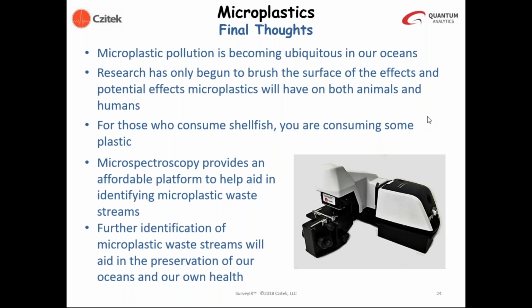So the first question, how long did the analysis of microplastic samples in the presentation take? Well, the collection of the infrared spectrum itself, measuring it, was a maximum of a minute. You have to collect the background spectrum, which is a blank, for those of you who aren't necessarily that familiar with FTIR. So it's a minute for the background and a minute for the sample. For these examples that we showed you, I think a couple of them were actually 30 seconds. So that proceeds relatively rapidly.